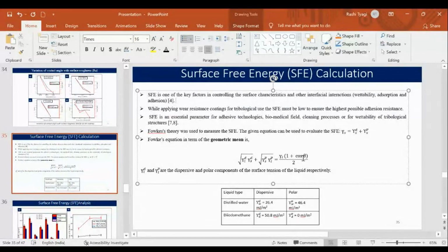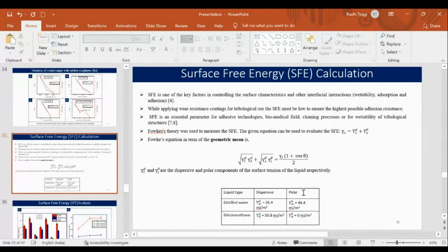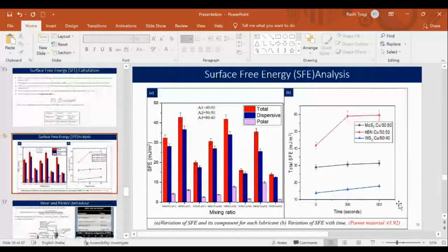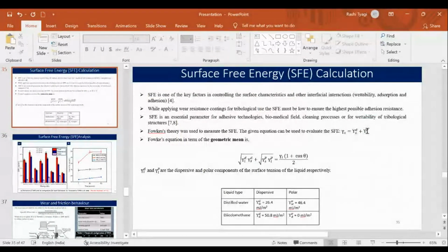Where cos theta is the contact angle that we have already obtained for the water. We will check the dispersive and polar components of the water. According to this formula, these are the dispersive and polar components that we have used: the dispersive component and polar component of free energy, the dispersive component for solid, polar component for liquid, and total. So these are the dispersive and polar component values that we have taken. By measuring this, we can get the surface free energy of the solid, gamma S. By obtaining gamma S dispersive and gamma S polar, we can get gamma S. It means the surface energy of the solid can be obtained from the dispersive component and polar component of the solid, which can be solved by this equation.